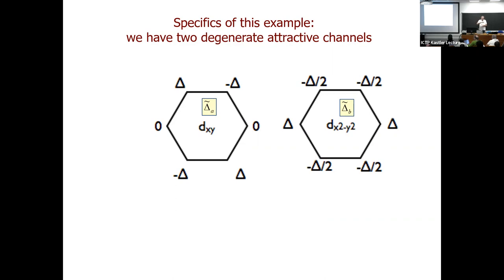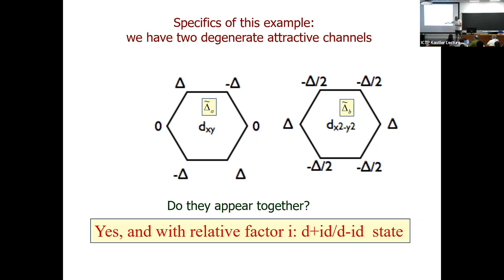You need to write down, of course, Ginzburg-Landau for this and derive all the coefficients. But then you ask, okay, wonderful, when they both appear, what happens? Well, they do appear with a factor of i or minus i. So you immediately get a chiral superconductor, chiral because it's a combination of dx square minus y square and dxy. And the superconductor breaks time reversal symmetry. And you get it instantly just because you have two degenerate channels.